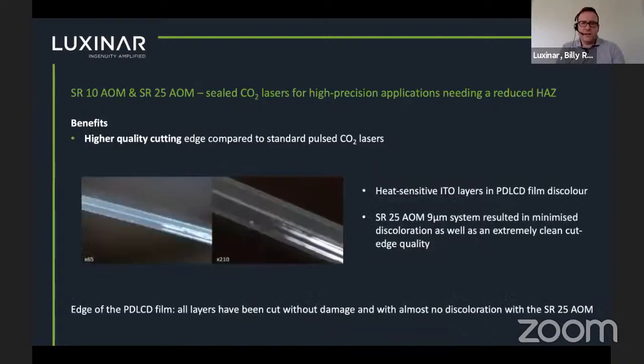And finally, it's a similar story here with heat-sensitive indium tin oxide layers. So they can suffer discoloration and also poor cut quality using long rise and fall time pulse CO2 lasers. And again, here we saw a vast improvement in the cut quality using an AOM laser.